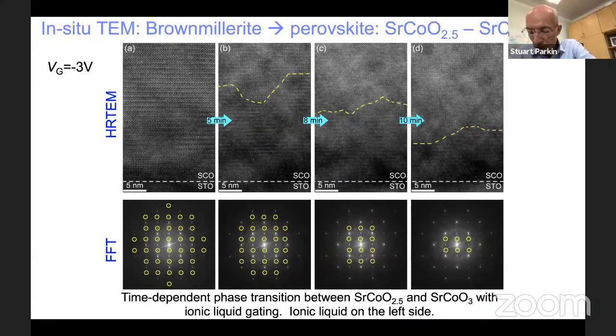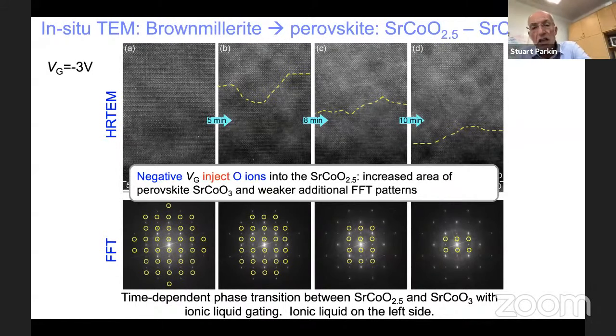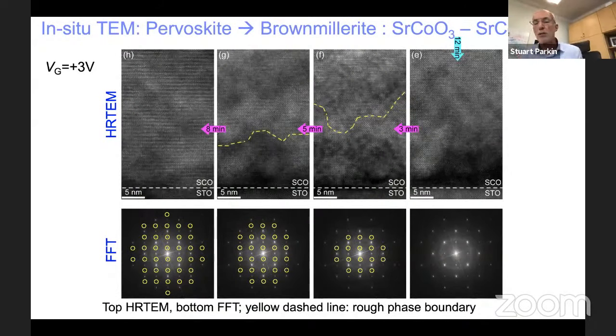In VO2, we've demonstrated up to a micron or so. And in this case, we can demonstrate up to several microns from the edge of the ionic liquid. We can remove the oxygen or put it back by reversing the gate voltage. This is what we're showing. We can inject oxygen ions from the ionic liquid to turn the brownmillerite into the perovskite, and we can go backwards. Now we can remove oxygen to turn the perovskite on the right-hand side to the brownmillerite on the left-hand side.